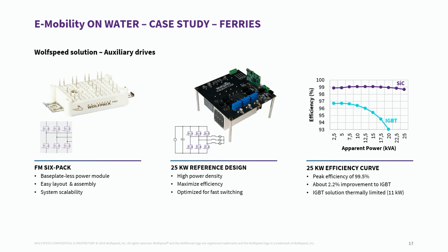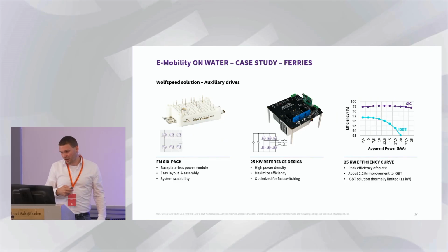Here we did a comparison between silicon carbide and IGBTs, but this is pretty obvious. If you increase the power, the losses are getting higher and higher for IGBTs, while for silicon carbide it's pretty flat across the power that we get out, which means that we can really make a difference by moving from silicon IGBTs to silicon carbide.